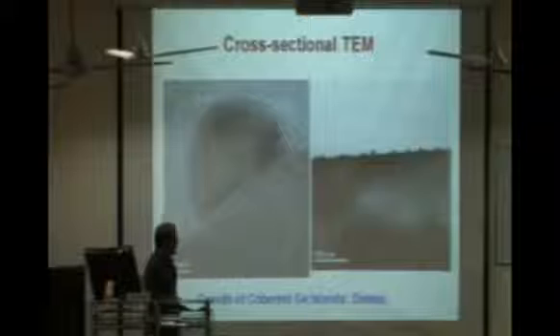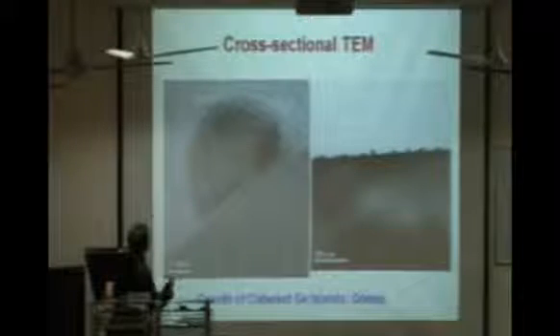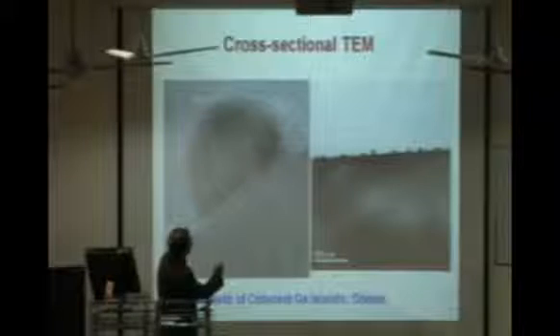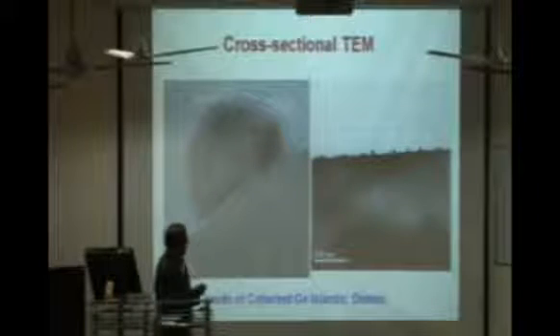If you have a very good lithography system, you can make single quantum dot devices. If you image a single germanium quantum dot, it looks like this. This is the silicon substrate, and there is a very thin layer we call the wetting layer, where the growth is in 2 dimensions, and then it suddenly transfers to 3 dimensions. As you see, there are very nice interference fringes, I don't know if it is visible from here, and this shows that the material is crystalline. This also shows a large number of quantum dots aligned on the silicon substrate. Now if you want to make devices, either you can make a single dot device or you can make multiple dot devices.